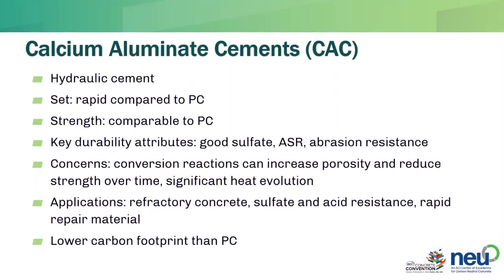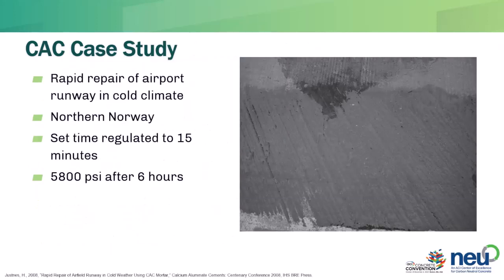Calcium aluminate cements, I won't go through this whole thing here. They are hydraulic cements that typically have a lower carbon footprint than Portland cement. Applications include refractory concrete, rapid repair material. Okay, so that's the other thing to consider, is that there's a lot of alternative cements out there. It doesn't mean that they're all direct replacements for Portland cement. Portland cement can be used in a number of applications, as you know. Calcium aluminate cements, maybe not a direct replacement. Just an example, though, there was rapid repair of an airport runway in a cold climate in Norway. They had about 15 minutes for set time and got 5,800 psi after 6 hours. So some of these cements, while they don't replace Portland directly, have really amazing properties.